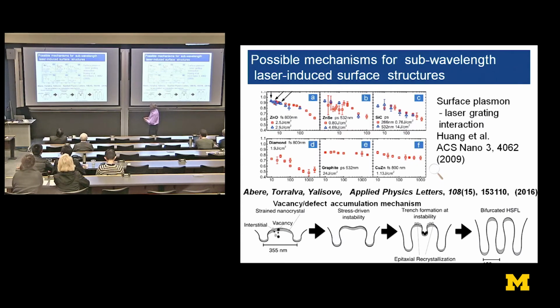as shown by this series of measurements here. And it's not just in one particular material. Antimony telluride is rather, you might consider, a rather exotic material, but it's also seen in simpler things like zinc oxide, zinc selenide, silicon carbide, diamond even, which is very strongly bonded, graphite, and copper zinc alloys. So it's a very general phenomenon driven by a coupling between a plasmon and an optical field.